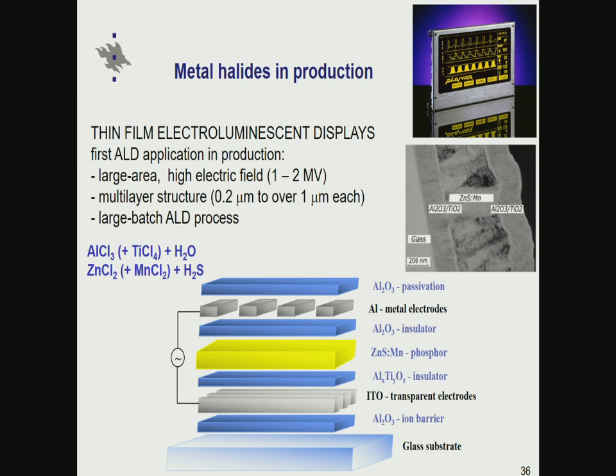Also these are multi-layer structures, so each of these layers is at least 200 nanometers in thickness. So the very first ALD application was not based on ultra-thin layers. Actually, these are some of the thickest layers in industrial production use of ALD ever. Especially this central layer, the manganese doped zinc sulfide, which is the light emitting layer, is typically at least 1 micrometer in thickness. And all these layers are produced using ALD in an industrial manner.